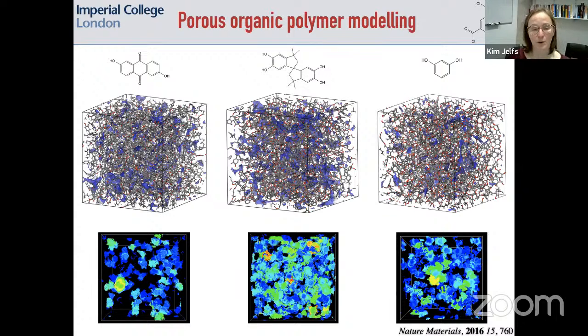What we find very useful is that you can compare the trends. In this case there are very subtle differences in the pore sizes, but the trends of those differences all tie up with the actual separation performance of these membranes. So it's a relatively simple way of looking at this, just doing the void analysis, but it's already very insightful, and it's what we found ourselves doing quite a lot.